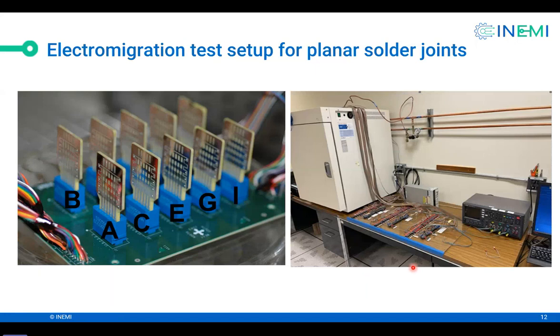Okay, so this is what the setup looks like. So this is in an oven controlled temperature, and this is a motherboard, and we put the daughter cards with each one has 5 solder joints. We plug them into this connector on the motherboard, and we have wiring that comes out of the board. You can see the wiring coming out, and then it goes to this table, and we measure current by using shunt resistors. Now, these are huge resistors. These are like 6-inch, they're massive. And the idea of a shunt resistor is when current flows through it, its resistance just doesn't change. So we can measure the voltage across the shunt resistor, and thereby we measure the current.